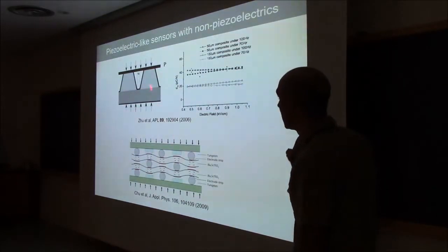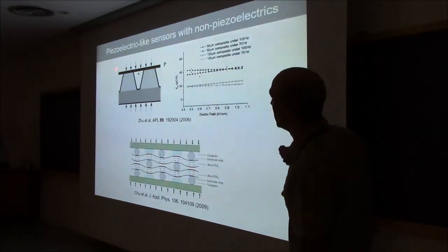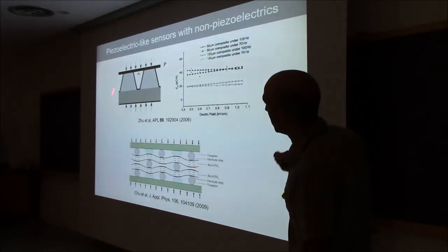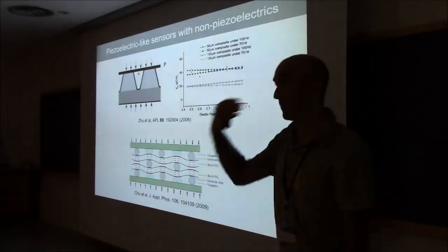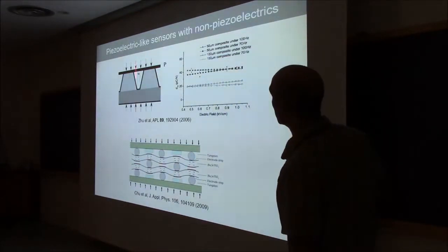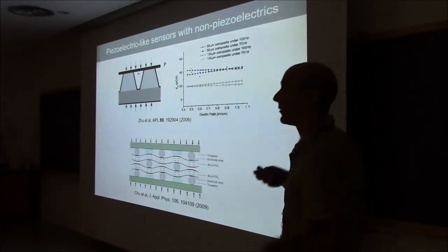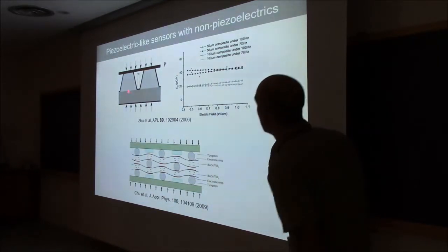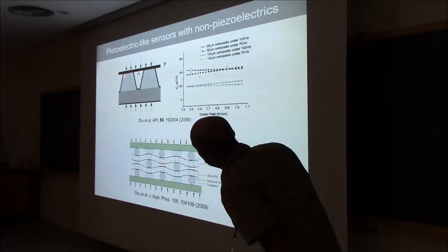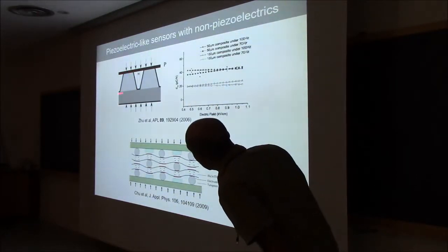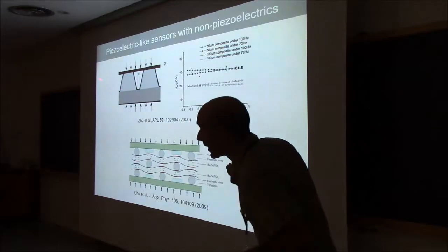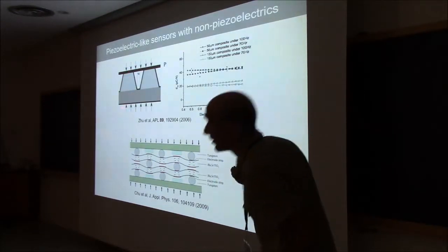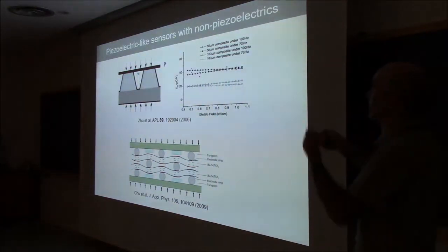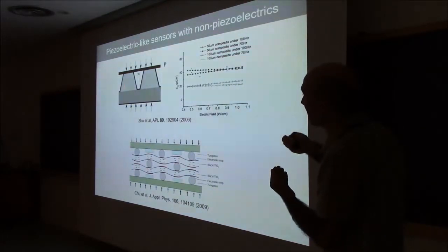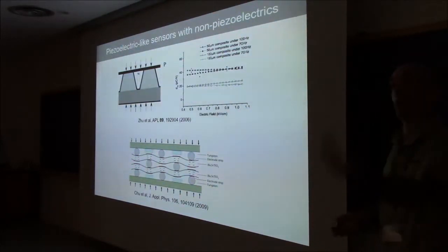What you do is you take your non-piezoelectric material and you engineer not the composition but the shape. As long as the shape of your material is asymmetric, when you apply a force to your material, the stress will be asymmetrically distributed. Here, because this area is much smaller than this area, the force per unit area, i.e. the pressure here, is much bigger than the pressure here. So you have a pressure gradient, which means that you have a strain gradient. Things will be more stressed here than here, and if you have a strain gradient, you have a polarization.